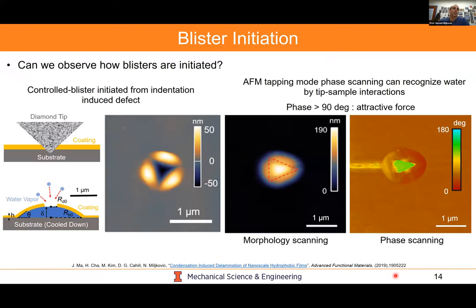And so what that enabled us to do now is to think a little bit: how can we now control pinholes to study how these blisters form? Can we control the geometry and the size of that particular pinhole to see how the blister mechanics change? And so what we do here is we use a process called nano indentation. This is a diamond tip that we take and we indent very finely into the coating and the substrate to form a defect.